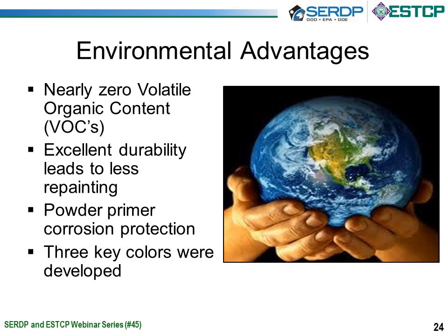The powder coating does use a powder primer, and the powder primer really is a highly chemical resistant, tightly cross-linked primer. So the fact that we put a powder coating primer underneath the powder coating top coat really adds to the corrosion protection also. If you buy furniture or metal equipment, everybody promotes powder coating as tough. One of the key things we point out is that the powder coating system is baked on, so it provides a very durable, hard, tough coating. And again, we have developed this in 3 colors. These 3 colors basically represent 98% of the business that's out there in CARC.